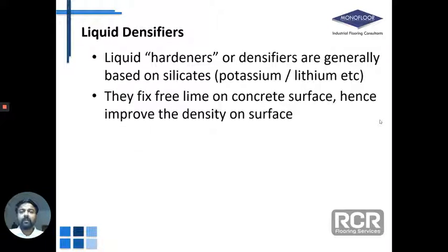Just to conclude this point with liquid densifiers: many times liquid densifiers are also referred to as hardeners. Just to clarify, liquid densifiers are silicates, mostly of potassium or lithium, and they fix the free lime on the concrete surface. Hence, when they fix the free lime on the concrete surface, they densify it. It's pretty much like what a varnish does to wood. It densifies the surface of the wood. The same way, silicates densify the surface of the concrete.